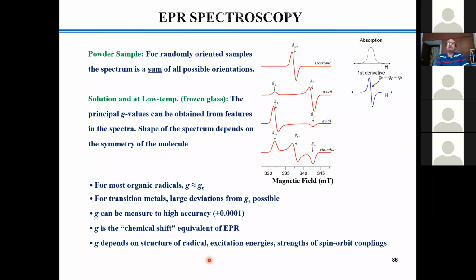So now if you have the g parameters, then there are a few issues we need to understand with respect to not the electronic structure mostly, but the molecular structures. The molecular structure, I already talked about it. The molecular structure could also be nicely represented by the EPR profile. For example, if you have a fully octahedral situation, I'm not talking about organic ligands, I'm talking about metal complexes, a purely octahedral situation. And as I told you, in a chelated system you will never expect a purely octahedral situation because of the chelate effect. You would essentially get a distorted octahedral situation.